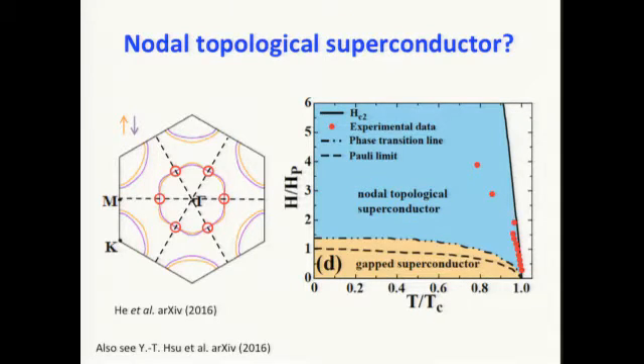It's true. There could be some coupling. For example, something I can imagine is that if you put your material on a substrate that breaks the perfect out-of-plane mirror symmetry, that could potentially destroy this point here because you induce a little bit of Rashba spin-orbit interaction. Right, then the gap is not completely closed there. Is there a way to prevent it? I'm not up to that point yet.